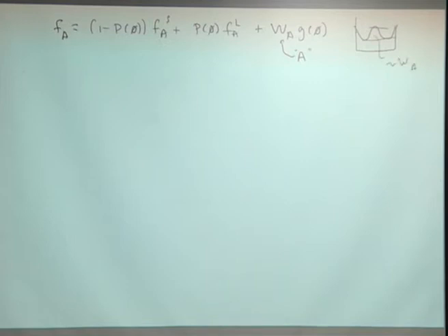Okay? And so this idea of an interpolation function here, where you interpolate from one phase to another, and then you add a well height between the two, appears all over the place. This is the standard way of interpolating between the two phases. Sometimes they use different forms for what P is, but you always see this general combination of an interpolated free energy and a well. Okay. And so you can do the same thing for component B.